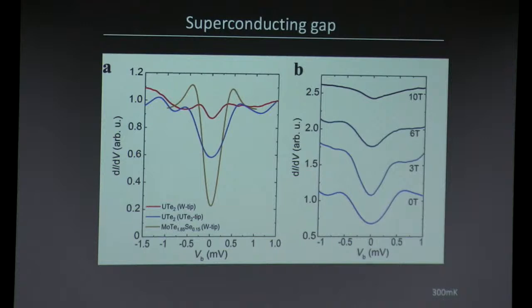This has been confirmed by other groups as well. Just to show you how shallow it is—shown here in red is the superconducting gap we measure on UTe2, and this is another material, molybdenum tellurium selenide, this is the spectrum for that. You can see it's got almost the same Tc, but with nice coherence peaks, and the gap goes pretty low. So the shallowness of the gap in UTe2 is actually a big mystery.